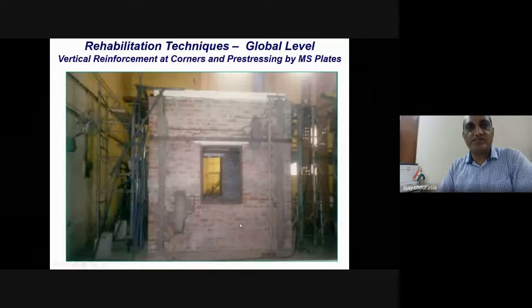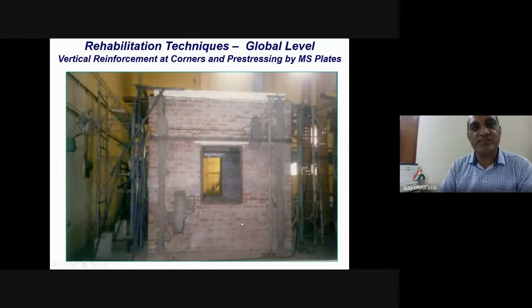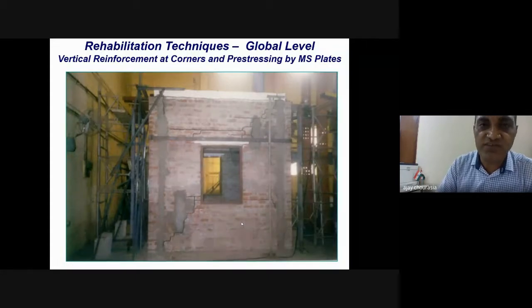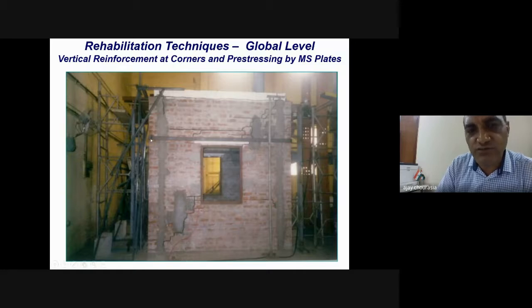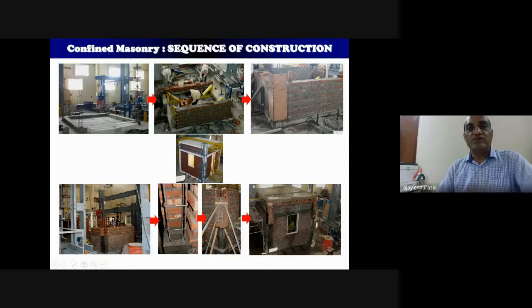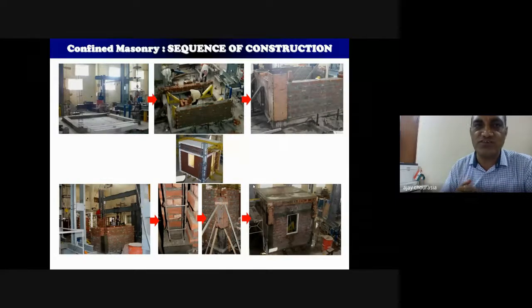As I mentioned, we have conducted extensive retrofitting investigations on unreinforced masonry. This is how the unreinforced masonry, after testing, was damaged and then retrofitted by providing MS flat at lintel level and corner vertical reinforcement, apart from the stitching of the cracks and grouting of the cracks. Now I will be focusing on the experimental investigation on a full scale, which was carried out on confined masonry. The sequence of construction, I would like to reiterate.